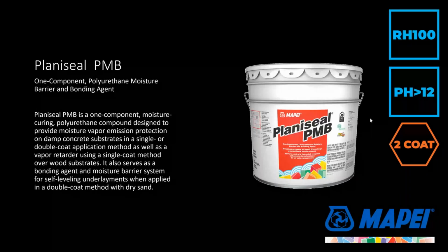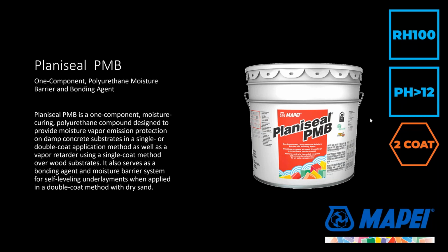Or you can go to Planaseal PMB, which is a fast set epoxy moisture vapor barrier. Requires 2 coats to create the 100% solution. Can be used on pH slabs up to 12, but does require the substrate to be porous. You cannot use this on non-porous materials, and it needs to absorb or soak into the concrete somewhat. This is one you definitely do not apply in thick layers. It's a very thin, neat film that goes down the first coat. If you put it on too thick, it creates a little crusty surface. It's not to be alarmed about that. That crust can be scraped off. The material underneath it will immediately cure, but you don't want those crusty things on the surface because nothing sticks to it. It becomes a weak part of the bond line later.